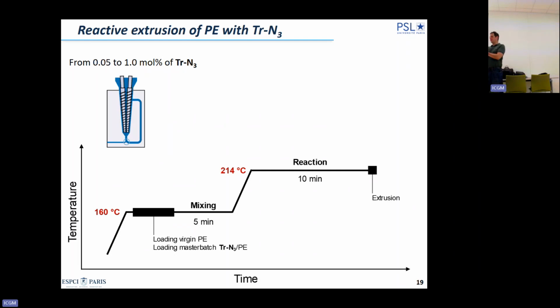And then we went for reactive processing. First thing we did is PE. So we take a commercial HDPE. We don't make it. We don't know how to do this, unlike our colleagues. And we introduce between 1 mole% of additive to 0.05 mole% of additive.